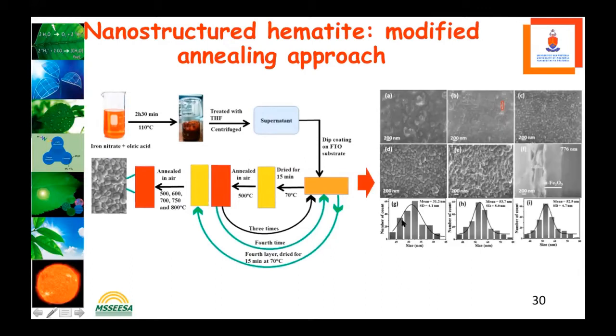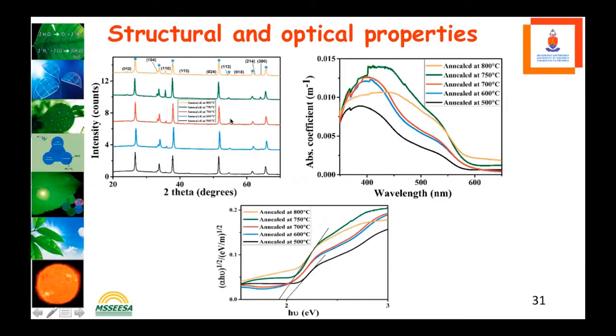And then when we look at, let me get something that can help me to see very clearly. On the nanostructuring, when we look at this particular area, the results thereof is that we find that the method of preparation is very influential in giving the size of the nanostructures on the surface here. You can see your A, B, C, D, E, F, G, H, I, where you can see where the nanostructures are becoming smaller. And generally, the smaller the nanostructures, the better the photocurrent that we have found.